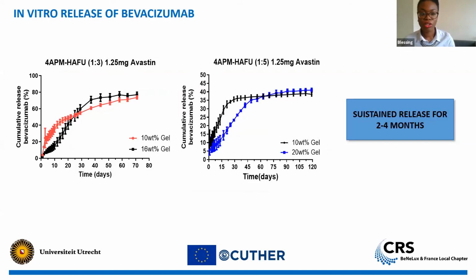Then it brings me to the most important question: for how long are we able to release these proteins in our in vitro studies? As you can see from this graph, we are able to make different formulations having different release rates, and we could sustain the release of bevacizumab in this case from 2 months to 4 months.